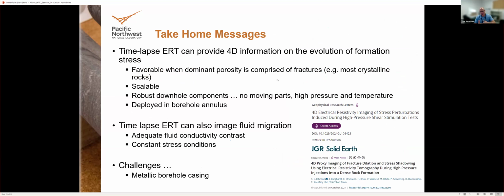We can monitor in crystalline rocks; imaging stress with ERT works very well because the fractures are compliant. Even the microfractures have large aspect ratios, so when we put stress on them, they tend to compress. It doesn't work as well in, say, sedimentary rocks where the pore spaces are more round because they don't compress as easily. I will say this method is scalable, so ERT works from very small scales to very large scales. Of course, resolution decreases as you get farther from electrodes, so that always has to be taken into account.